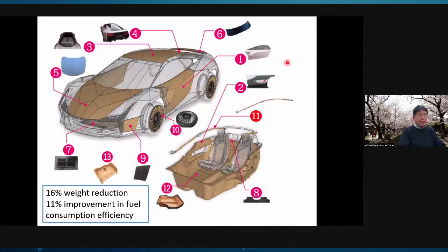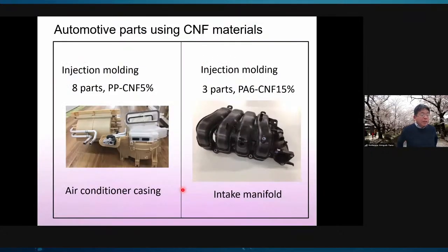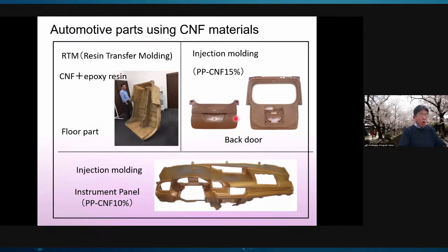Here you can see 13 types of automotive parts onboarded on NCV. In total, we could estimate a 16% weight reduction of the automobile by cellulose nanofiber materials and an improvement of fuel consumption by 11%. Although we didn't onboard them on NCV, we manufactured an air conditioner casing consisting of 8 CNF polypropylene composite parts, and the intake manifold consisting of 3 CNF polyamide 6 composite parts. We made a big floor part by resin transfer molding, and the back door and instrument panel by injection molding.